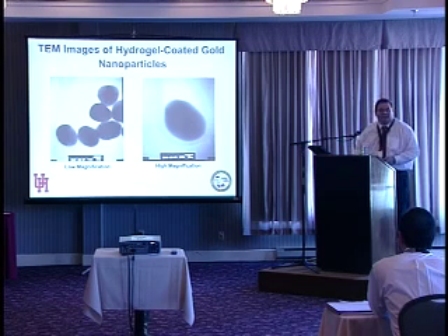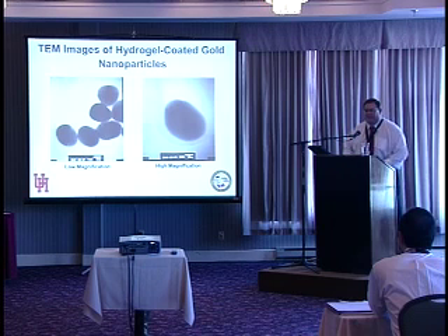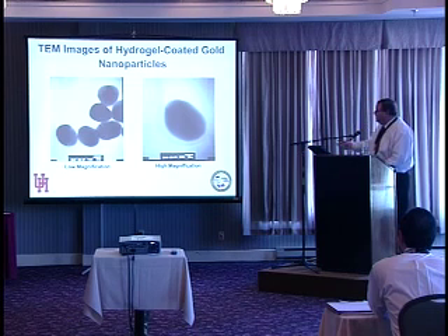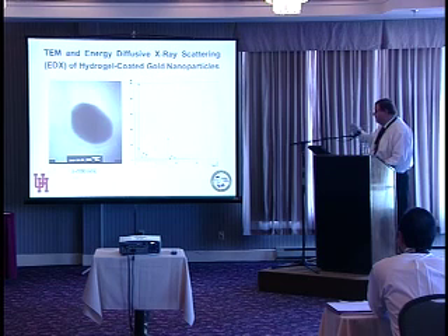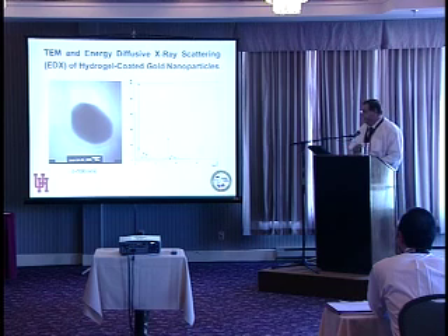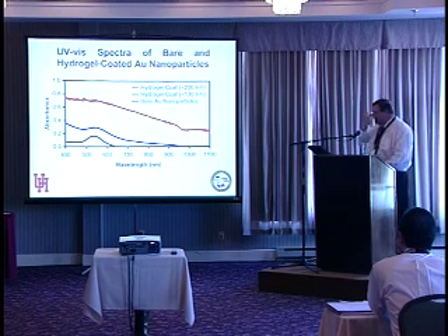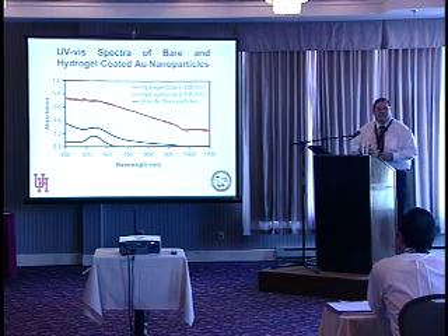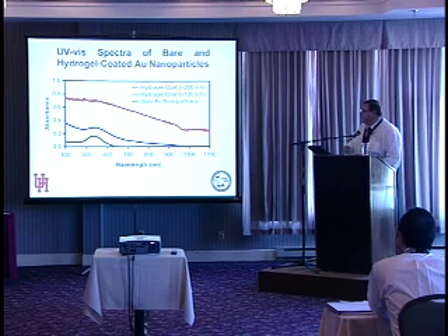And of course, it looks very thin in these images because the technique that we're using is TEM, and in the process, we didn't take any precautions to exclude the evaporation of water when we put these things under ultra-high vacuum. So the thicknesses are less than what we measure with dynamic light scattering. We can do EDX analysis that proves that we have gold there in the center. Of course, these initial studies that we did were not with nanoshell particles themselves. This is just simple gold nanoparticles to try to work out the technology.